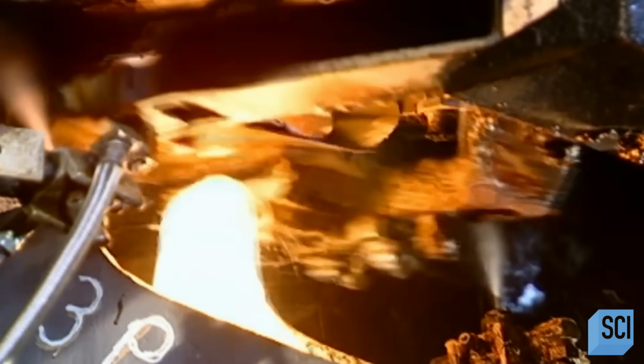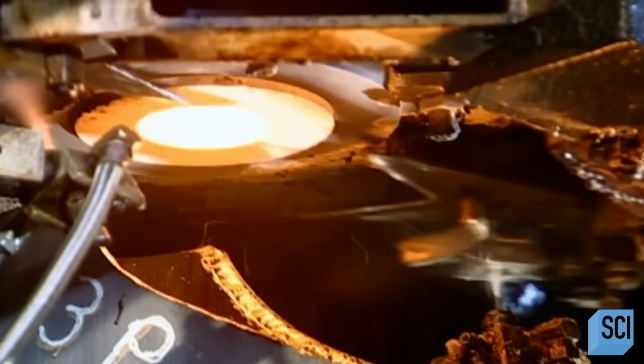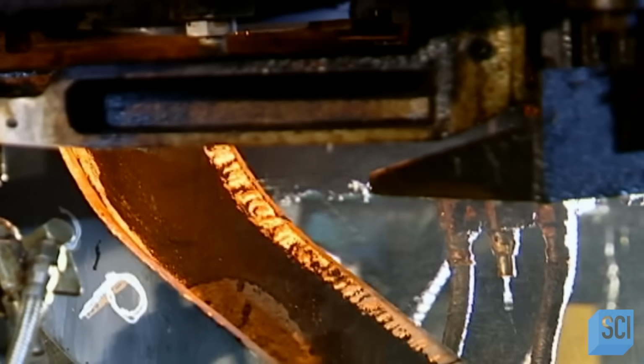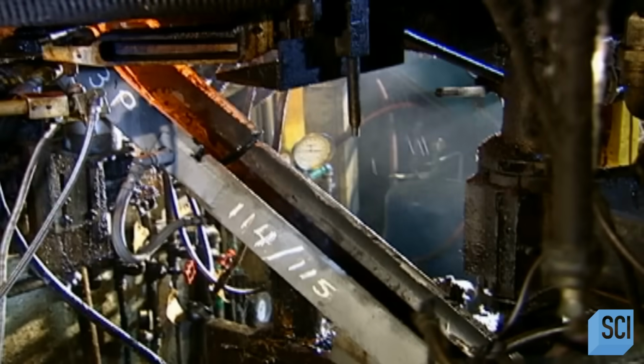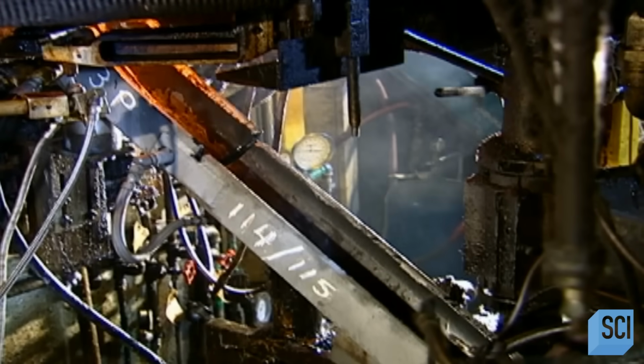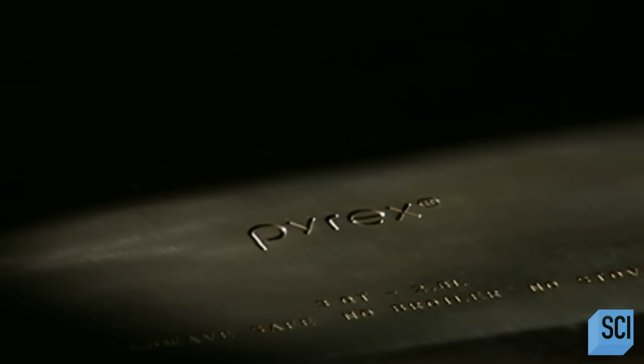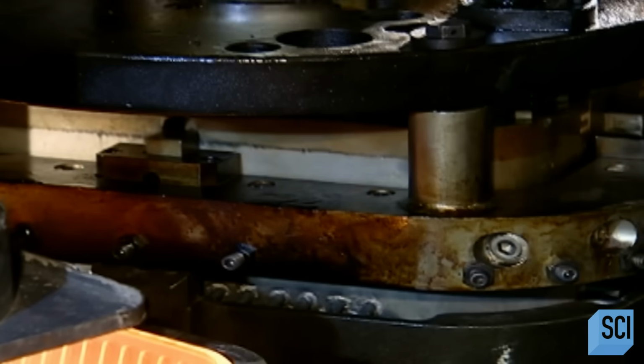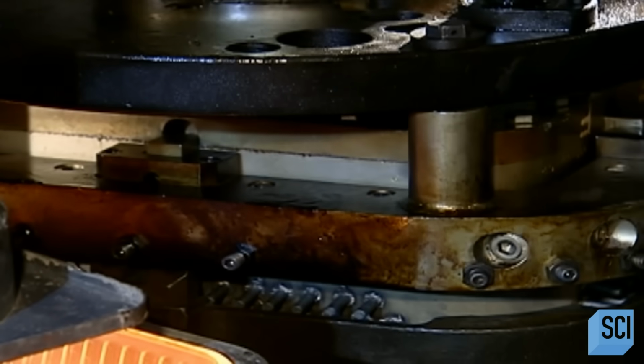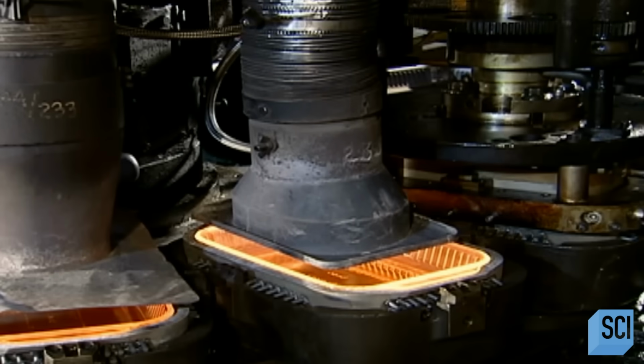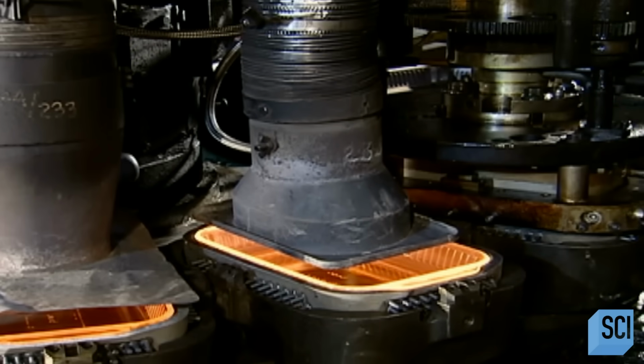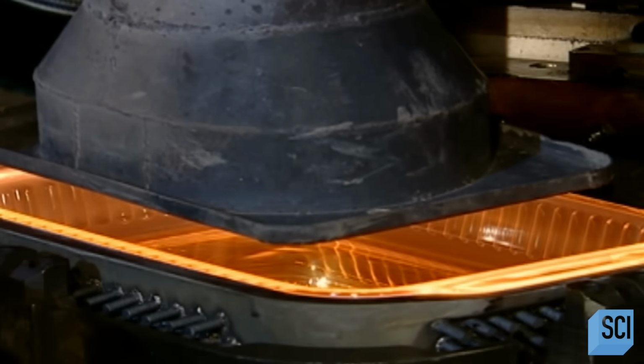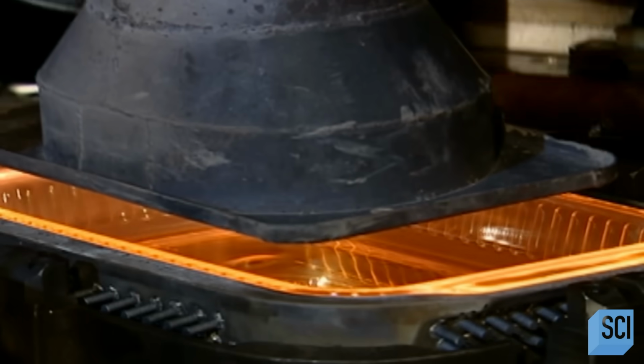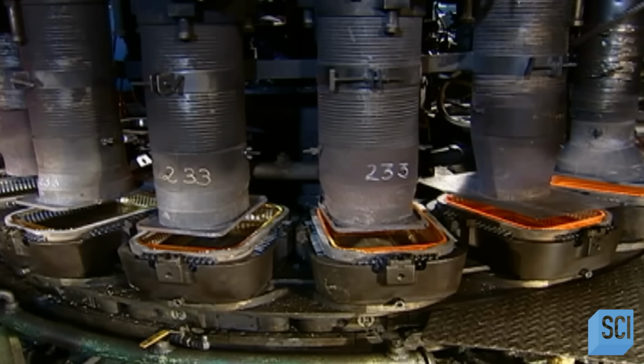On its way out, mechanical shears cut it into gobs. The gobs slide down a water-cooled chute and drop into a baking dish-shaped mold. There are 16 molds on a rotating table. As it turns, the table delivers the gob-filled molds to a plunger, which presses them into the baking dish shape. Continuing to rotate, the table positions the molds under blowers. They cool the freshly molded glass so it holds its shape.